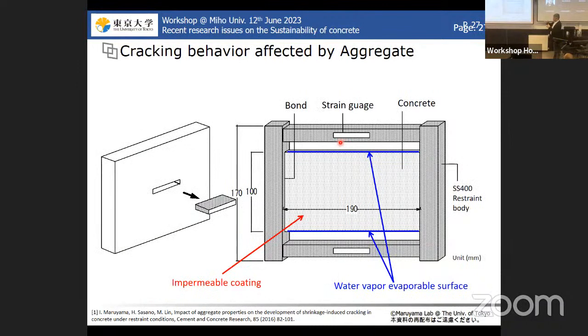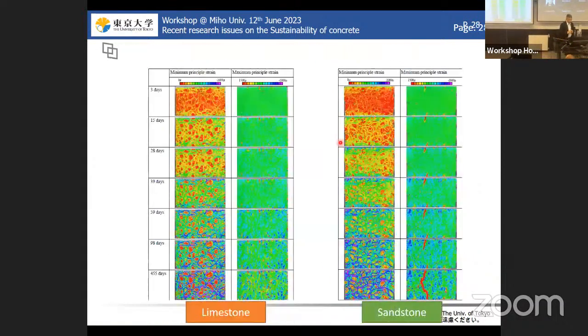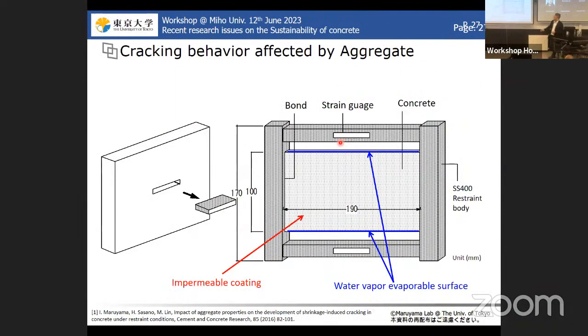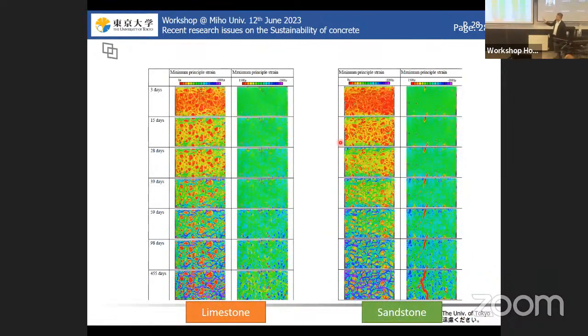We cut a small piece of the concrete, restrained it using a frame, and by using digital image correlation, we try to capture how the cracks develop in the concrete. I used an impermeable coating on the surface of this side, and I exposed the specimen to ambient air on this side. So we try to simulate how the surface cracks develop from outside to inside using this experiment. The left side is the limestone, and the right side is the sandstone.